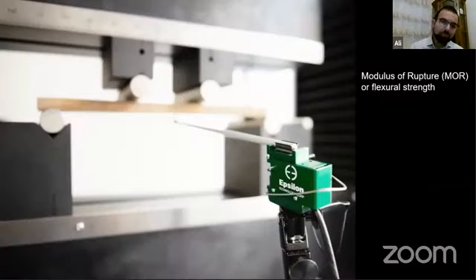But one of our main challenges, our team's challenge, was the lack of standardization. ISO has a, I would say, outdated standard for testing materials like bamboo. Unfortunately, with many of those standards that we started to follow, we had problems, because when we changed the bamboo species, either the bamboo column was very thin or the wall thickness was very thin, we were not able to follow the standards, and that made our testing a little bit tedious and time consuming. So it took us almost 1.5 years to test the most common bamboo species from this region.